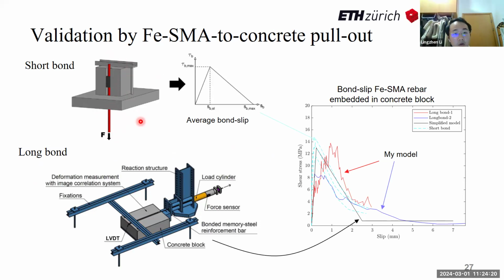The typical method to measure the bond behavior between steel and concrete is to use a short bond length, which is typically 5 times the rebar diameter, and measure the force-displacement behavior. Then the shear stress is calculated as the tensile force divided by the rebar perimeter and the bond length, so that we have this average bond slip behavior.